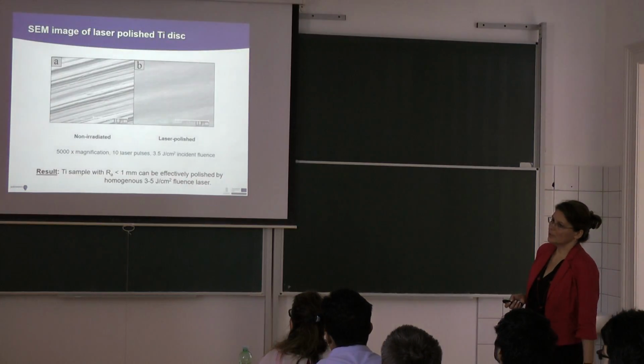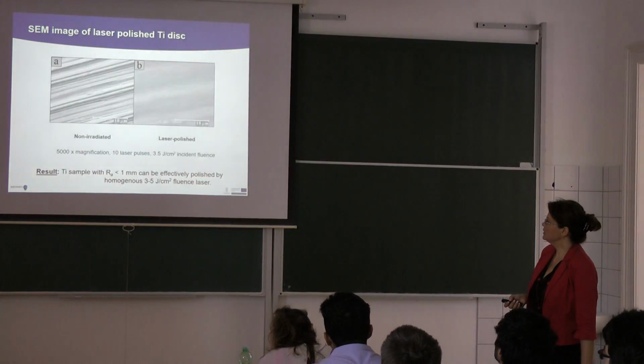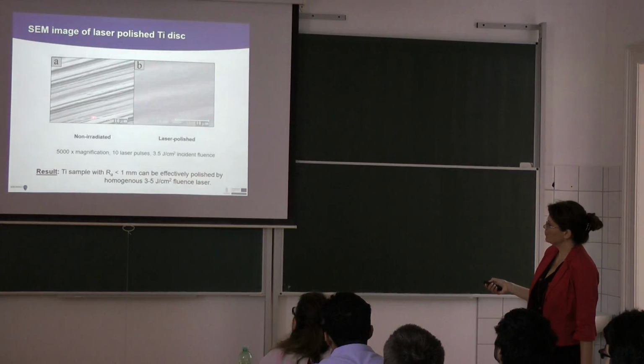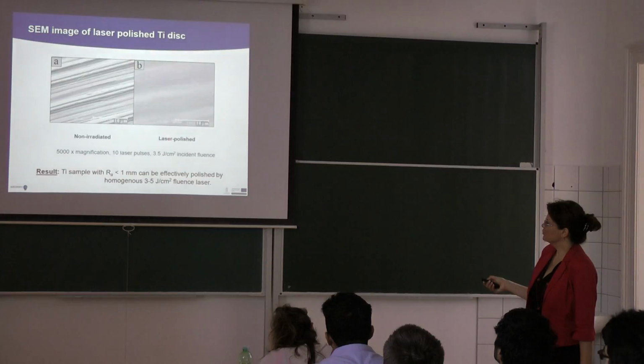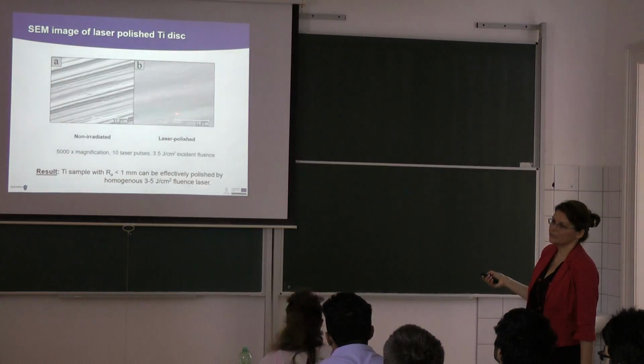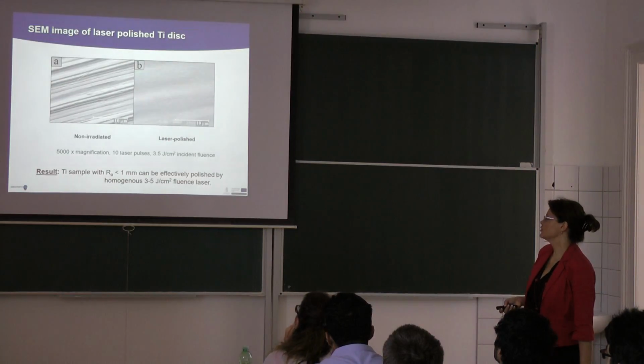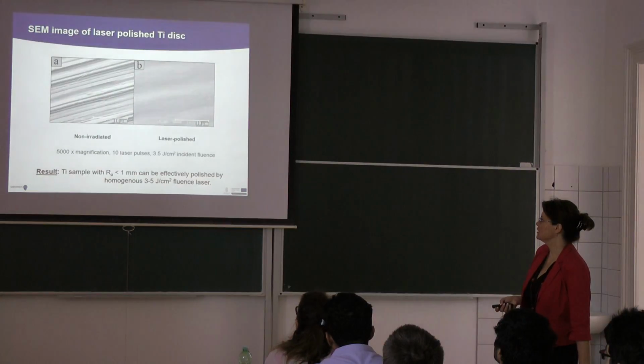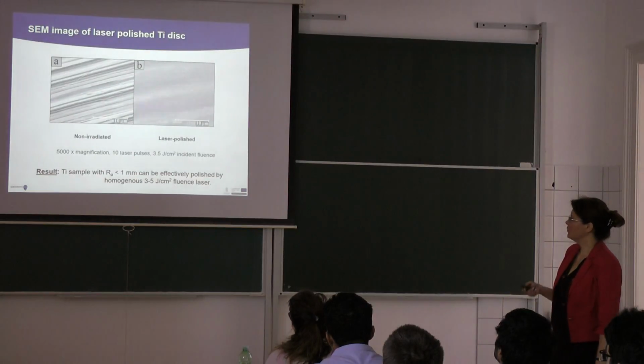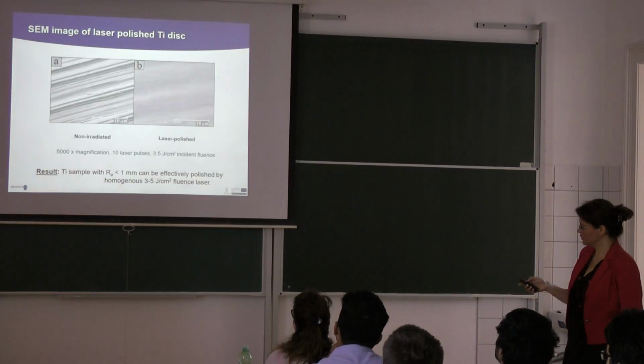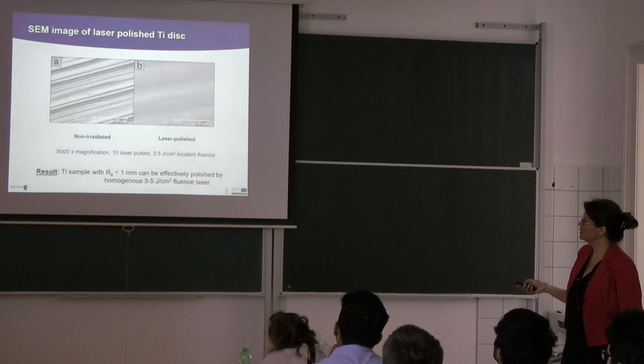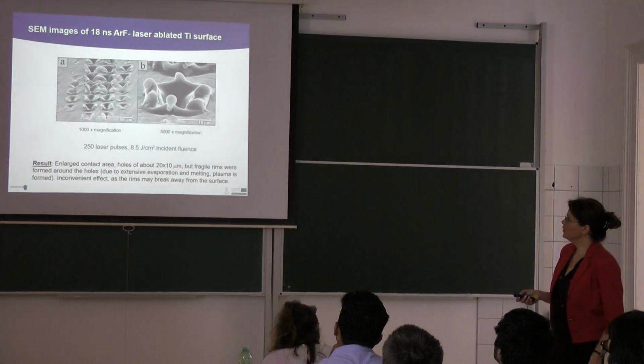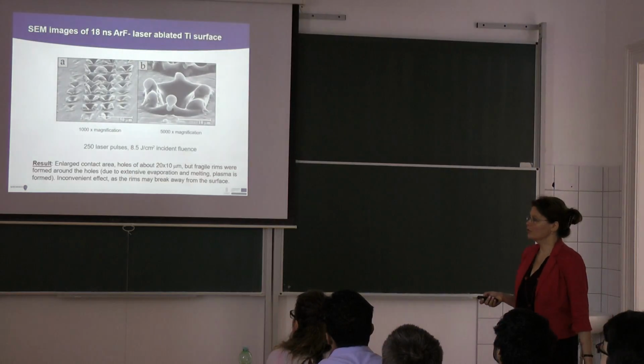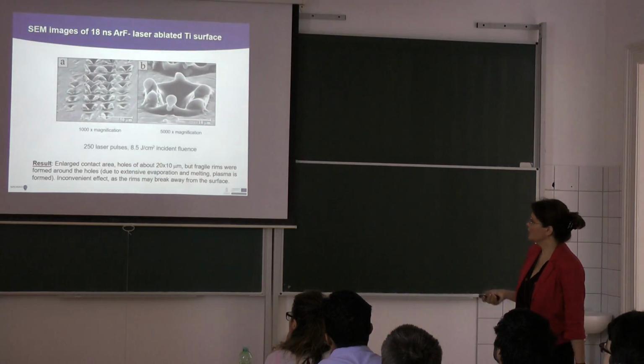Now what we could establish in these results is that if you have a machined surface and you see the same magnification, after you apply the laser, you will have a very nicely polished surface. Of course, it is still very expensive to use this kind of technique, but as it evolves, you can use it for polishing dental materials also.